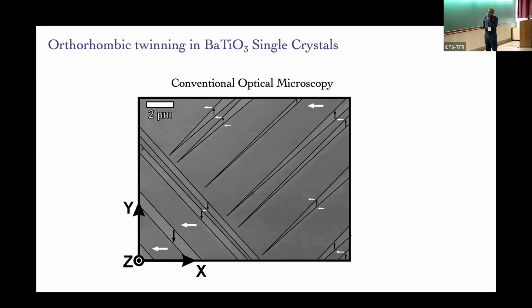You'll see them. So regular optical microscope, you put one of these single crystals, you'll see beautiful domains like these. These are electrical domains, the polarization, the direction in which the titanium is popping, for example. So this is like step ladder type domains. There is another step ladder going that way. When they sort of start trying to meet, there's a lot of stress around here. So these guys, instead of running into this, they form little needles, and there's a lot of stress here. Okay. So local stresses and fields could stabilize something else. And I'm going to show you those monoclinic phases will start showing up in this sort of region. Okay. So regular optical microscope, everything looks okay. These are tetragonal domains, classic phase diagram.